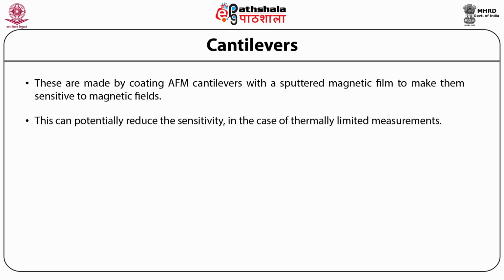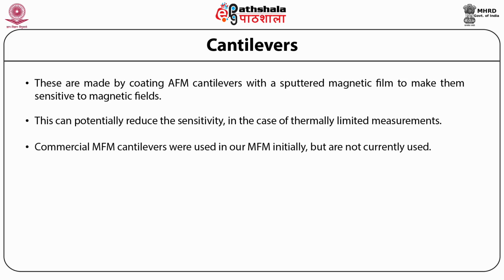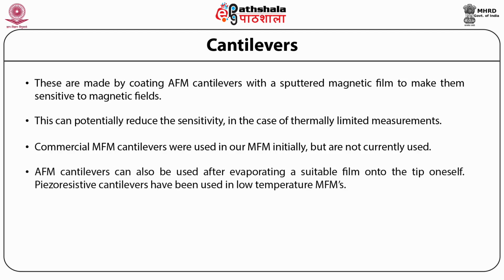Also, the magnetic moment tends to be fairly large, which can be useful for generating a large signal when imaging a hard magnetic sample which is not significantly disturbed by the tip field, but it can be problematic when imaging a sensitive sample such as vortices in a superconductor. Commercial MFM cantilevers were used in our MFM initially, but are not currently used. AFM cantilevers can also be used after evaporating a suitable film onto the tip oneself.